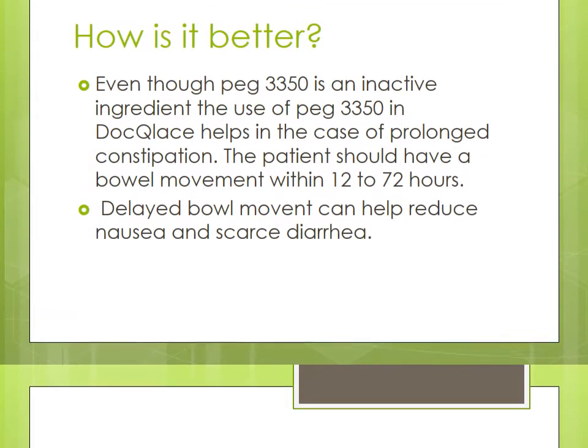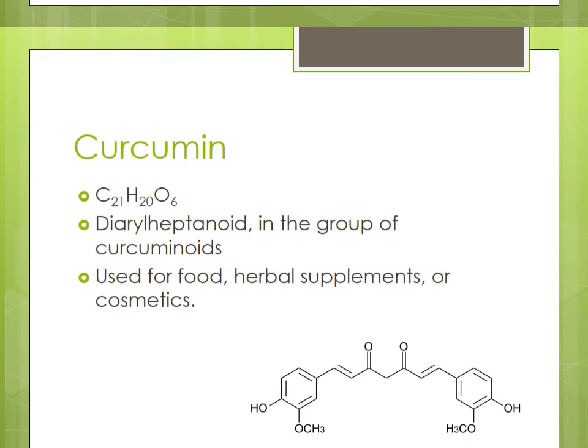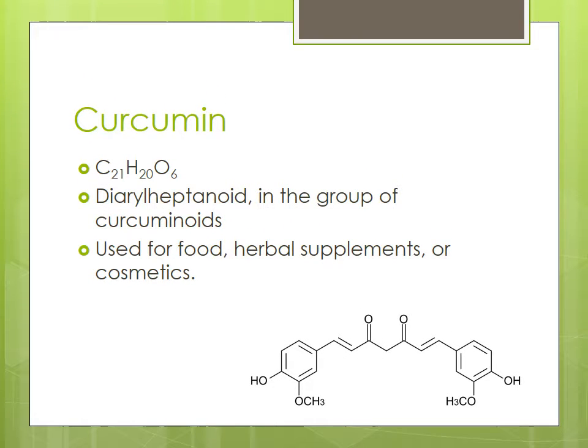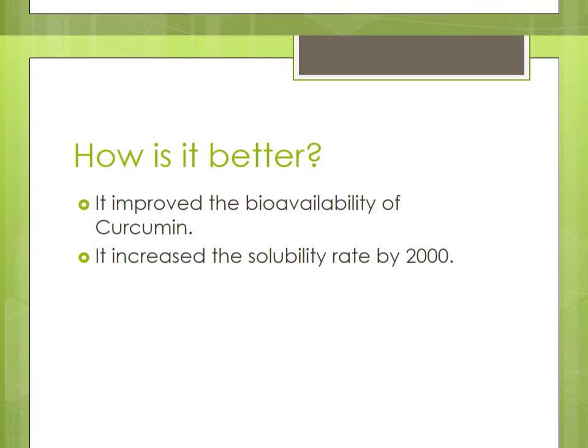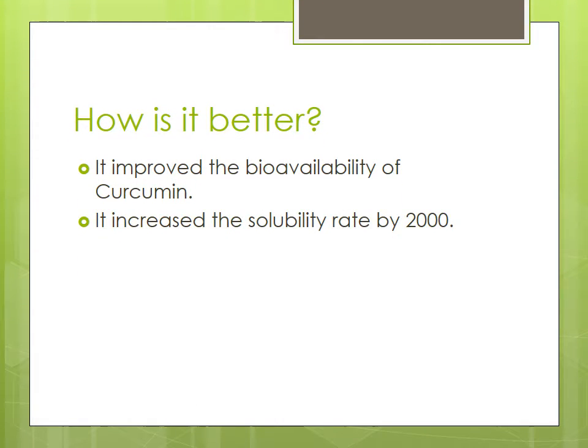Curcumin. In this article, they use PEG with curcumin to see if it would improve the solubility. How is it better? It increases the solubility rate by 2,000-fold and also made the release rate more constant. It also increased the bioavailability of the curcumin nanoparticles.